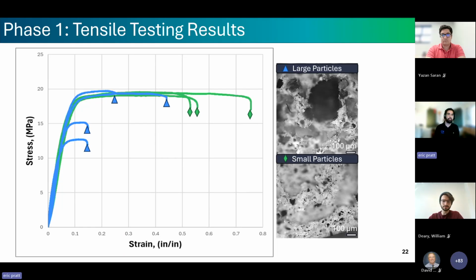Large particles create a small number of severe stress concentration defects. In the image on the right, you can see a large void where a particle used to be. However, small particles spread the same stress across many smaller sites instead, and you can see the difference in how they fail. The small particle samples show pronounced necking that's visible as these ring-shaped deformations at the fracture surface, which tells us we're looking at a significantly more ductile failure mode.